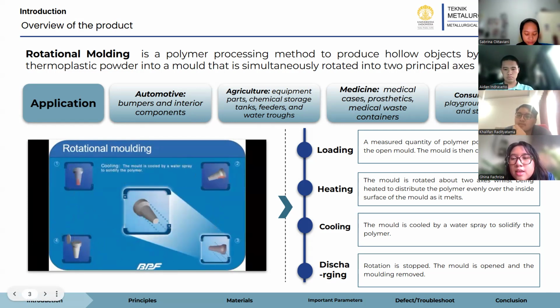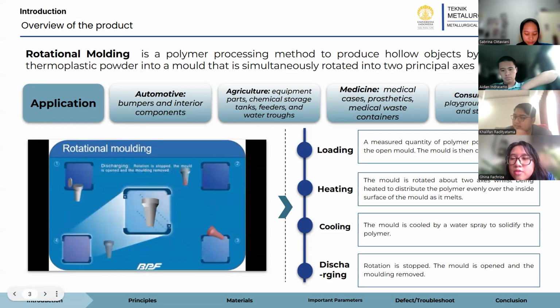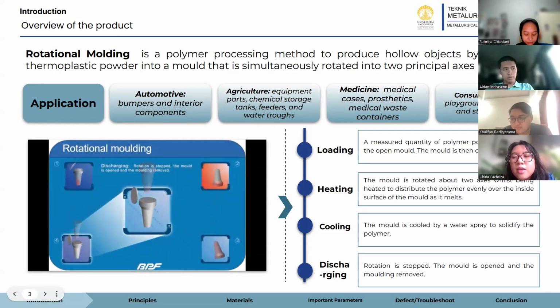After sufficient heating, the mold enters a cooling stage, during which water or air is used to reduce the temperature. This cooling process solidifies the polymer, ensuring the object maintains its shape and structural integrity once removed from the mold. And the last phase is the discharging phase, where the polymer has fully solidified, the rotation stops, the mold is opened, and the whole product is carefully removed. The final product typically requires minimal finishing, as the process inherently produces smooth and uniform surfaces.